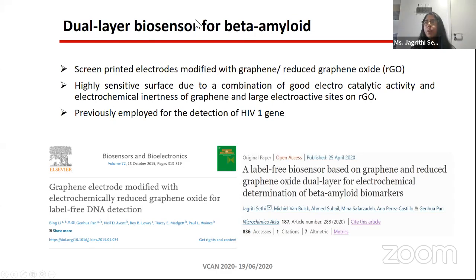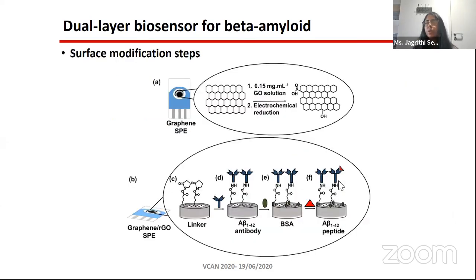We have employed a similar structure for the detection of the HIV-1 gene, and we recently published it for the detection of the protein biomarker beta amyloid in 2020. What we did is we took a graphene screen printed electrode, and the first step is to modify it with graphene oxide solution, which we then electrochemically reduce to produce the RGO graphene dual layer electrode. The next step is the modification of the linker.